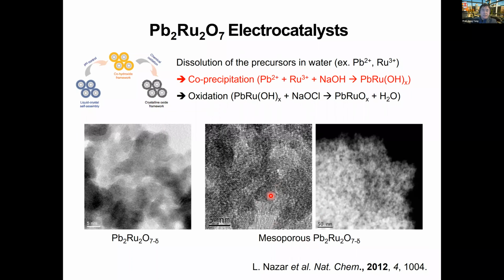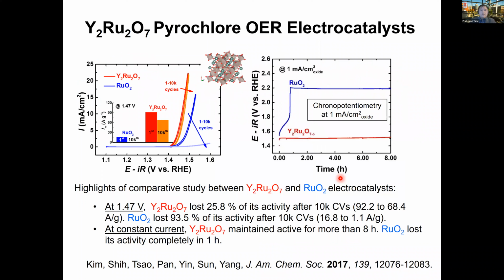It turns out that mechanically, this kind of structure is not that stable, so that leads to a lot of issues. So we entered this area thinking about developing a stable catalyst, focusing on the yttrium-based system, among others. In the early work, of course, we had to test out a variety of pyrochlore structures. In the first batch, we tested about 20 to 30 different kinds. And this is the one that was screened out with decent stability, also very nice activities.